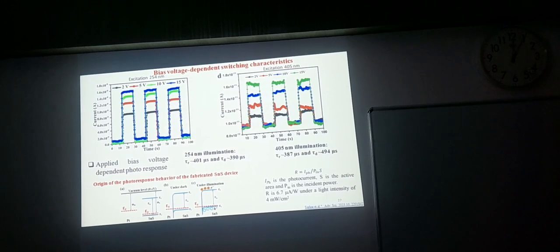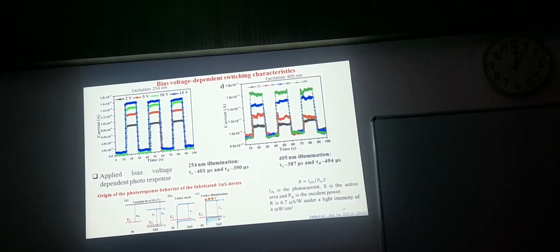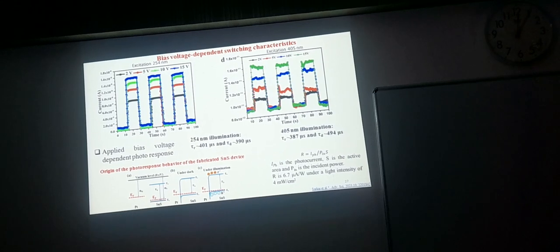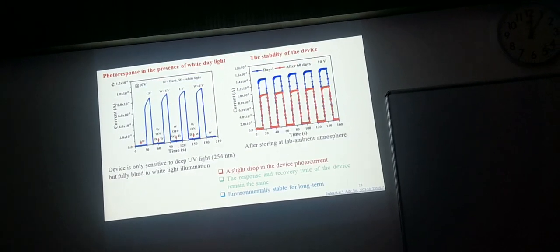Not only that, we have studied the interface physics in the system, what is actually happening at the gold electrodes and this tin sulfide. We realized there is charge transfer from the single layer tin sulfide to these two electrodes in the system. I'll not go into detail. Here we basically find out the response time and the decay time of this system, which is pretty good. I will come to the next slide.